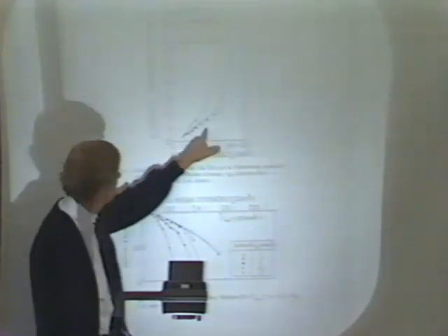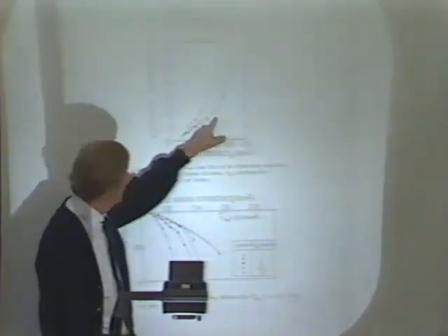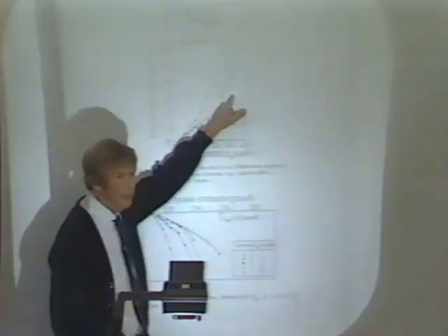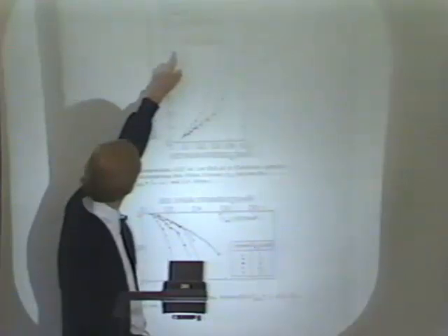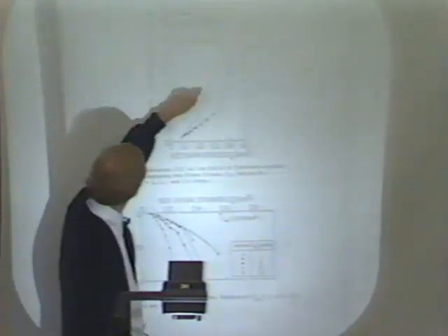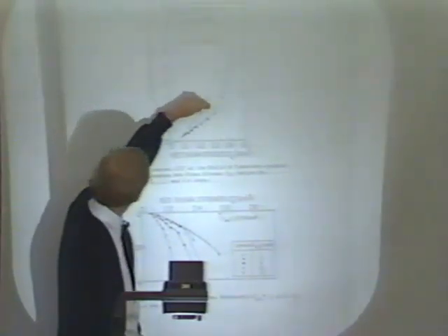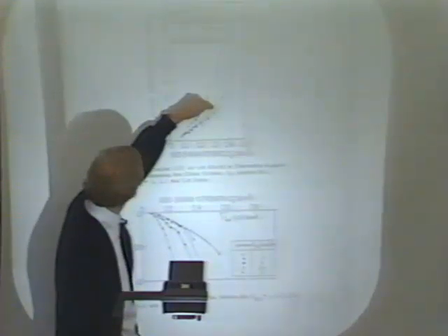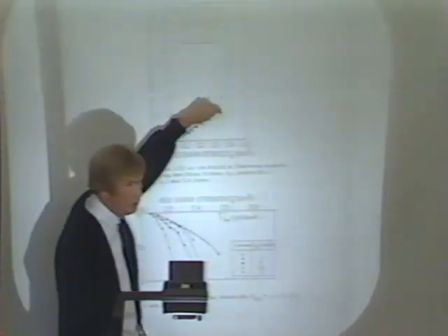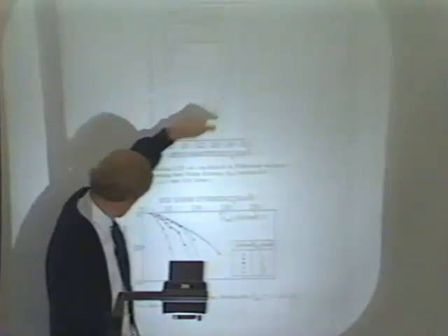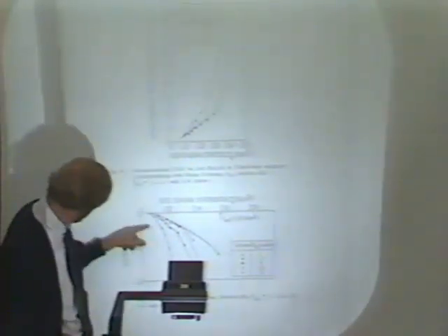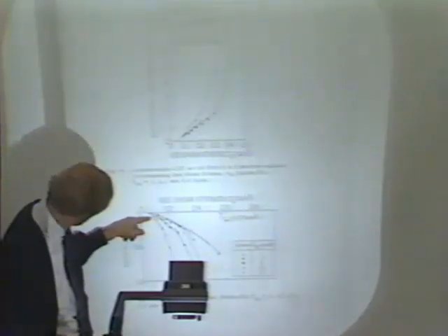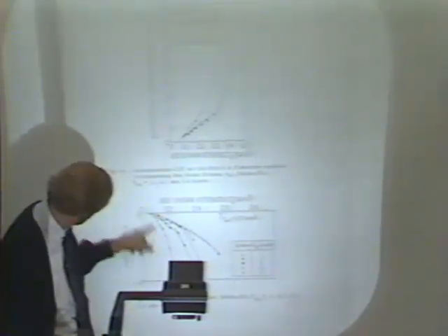So he observed gelling also. And he gave the strength of the bed as this data. You can see that at 1 day, it was much weaker than it was on subsequent days. And this is depth in centimeters, and this is only 1 centimeter, so you can see that what's happening is happening right close to the surface of the soil. And in fact, gelling continues, but the structure is more open up here.